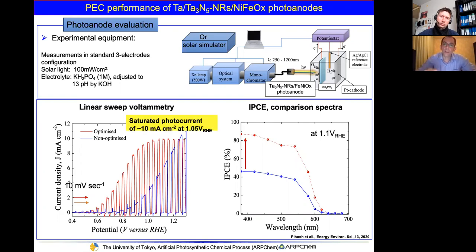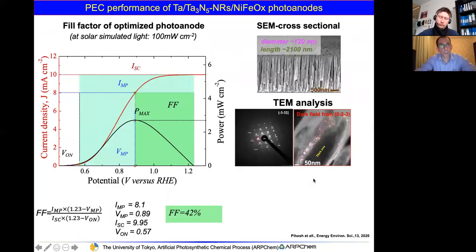Okay. And if we now look at the quantum efficiency for both materials, we can see that the optimized photoanode shows us almost twice the enhancement in this region. Okay, and then we calculated the fill factor.